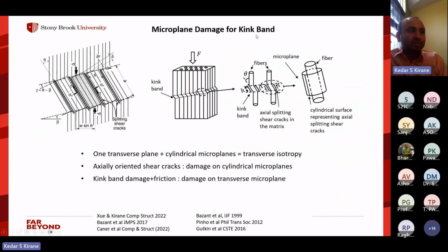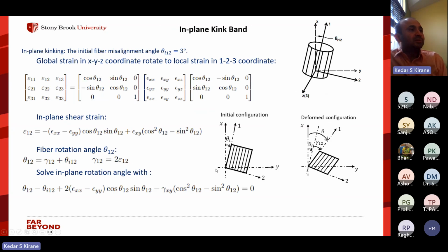And how we then capture the kink band formation is as follows. So the hypothesis is that in the kink band, it is all shear localization. And that shear is parallel to the fibers. A lot of it is parallel to the fibers. So because we have this cylindrical microplane system, we have easy access to the shear acting on the cylindrical microplanes. And we also have shear acting on the transverse n plane, right? The transverse plane. So what we do is we define a simple damage law, which is driven by the shear acting on the cylindrical microplanes and the n plane. And we use that damage to capture the overall failure of the composite. Okay. So that is one feature where we have simple damage laws on the cylindrical microplanes and also the transverse microplane. And the very important key feature is the orientation of the cylindrical system of microplanes.